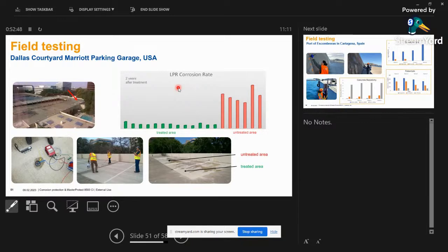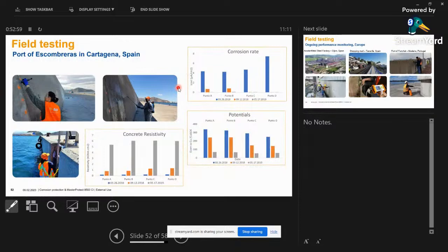LPR gives the direct measurement of the corrosion current. We have not only measured corrosion current, we have measured the corrosion resistivity, and we have also measured the potential. So in the next slide, you will see that field trials showed a huge drop in the corrosion current with time. As you see, it was applied on 26 March 2018, and as time passes, you see the untreated samples have higher corrosion, and the treated samples start to reduce in corrosion. Potential difference, huge difference. Concrete resistivity goes up.